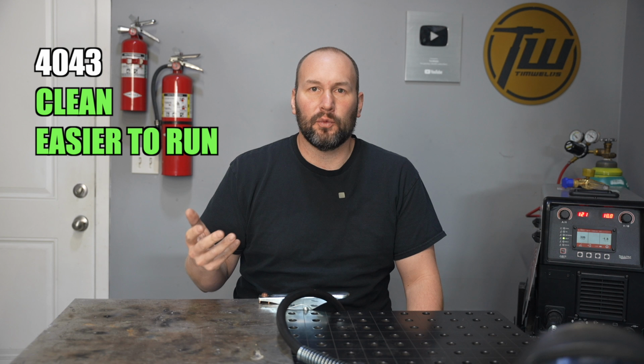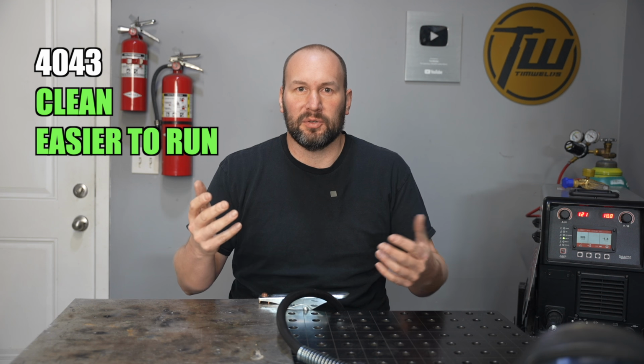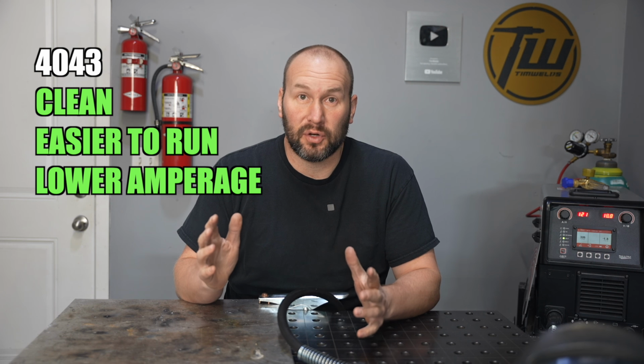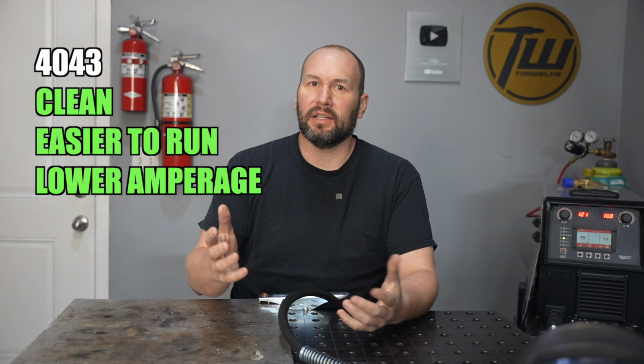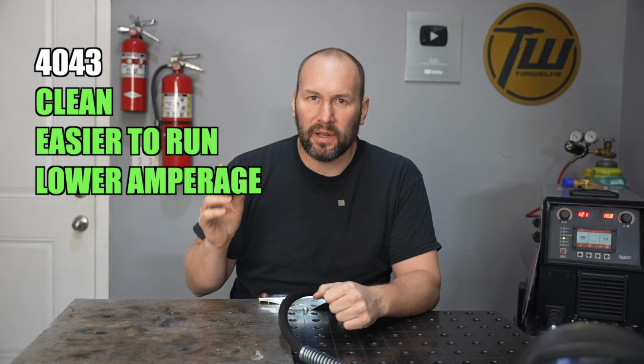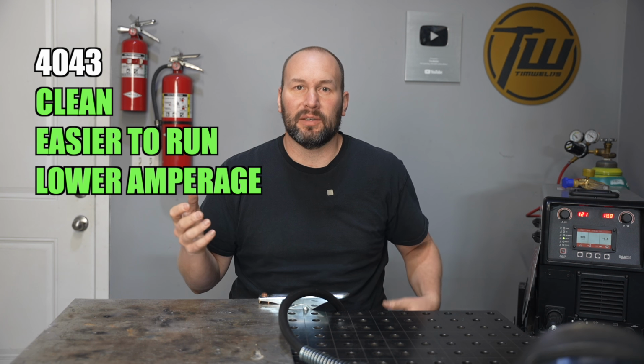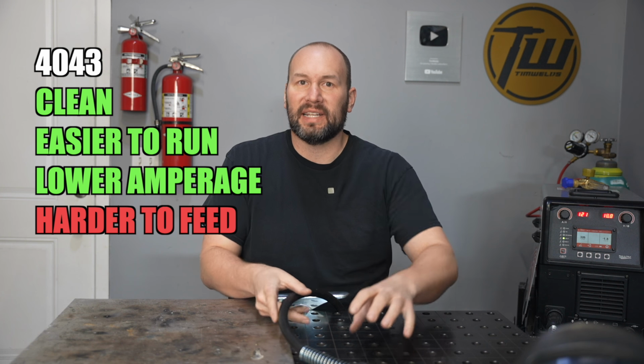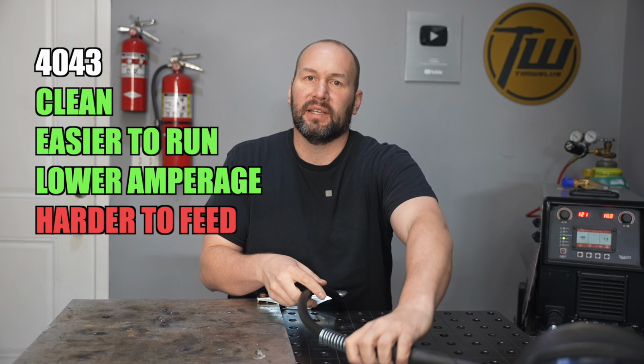4043, which is my pick whenever I'm able to run it, runs really smoothly. It's a very clean puddle and clean arc, and just overall is easier. It'll also run with a lower amperage machine in general if you're struggling with that. Now there are a few cons to 4043, and one of those is the softer alloy makes it more difficult to feed, so it's more important to have a good setup to weld with it.